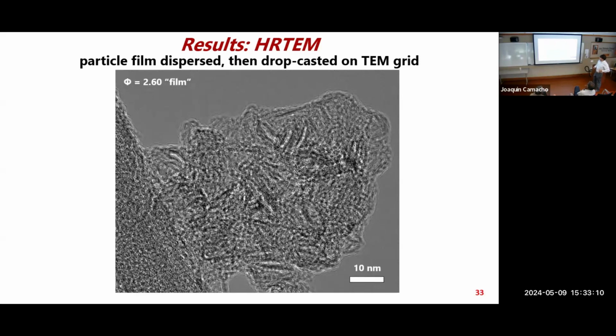And I'm still working on ways to make better samples to get these more dispersed, to get more details of the particles rather than the clusters, because in the time and the conditions we have, they're not forming these big, like 100 nanometer agglomerates. That's not happening in the flame. It's just when you prepare the sample, they coalesce like this.